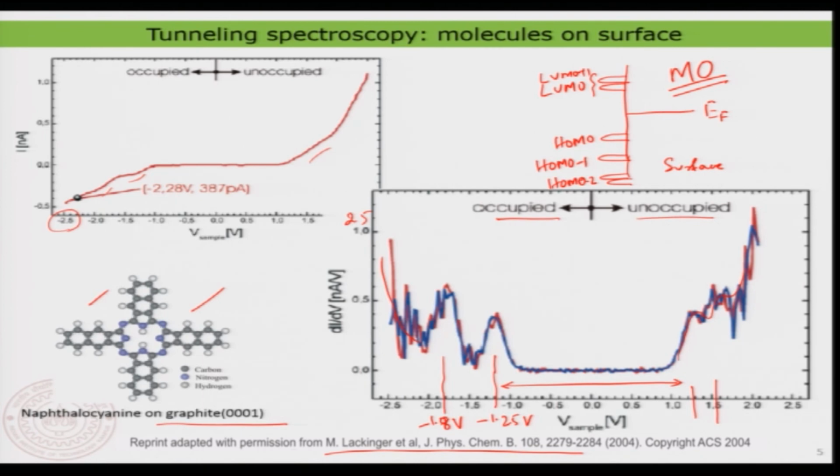And also I just want to mention one quick important point here. You would notice most of the time that we typically measure electronic structure around the Fermi level to something like plus or minus 3 electron volt, and not more than that, because beyond that certain difficulties also appear in tunneling spectroscopy due to other effects like field emission.